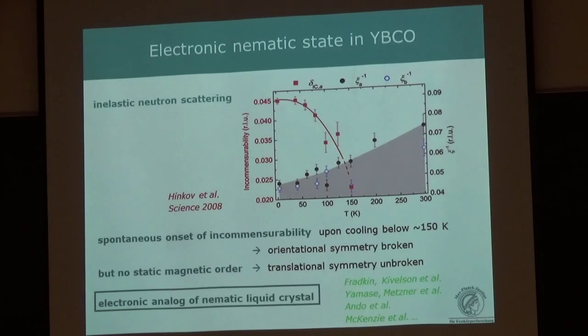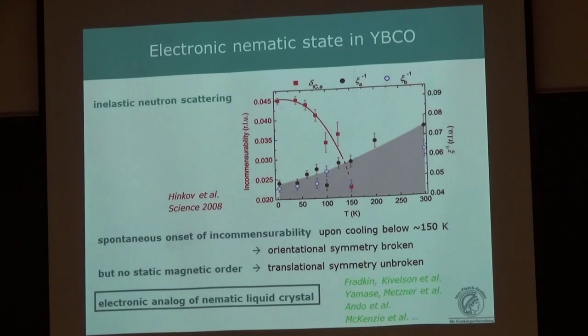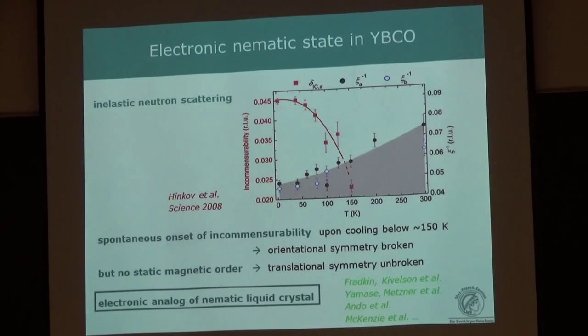Rather, this orthorhombic crystal distortion acts as an additional field—just like a field applied to a ferromagnet broadens the phase transition, but you can still call it a ferromagnet even though symmetry is already broken above the Curie temperature. This incommensurability was extracted from low-energy spin fluctuations; it's the same incommensurability that eventually characterizes the quasi-elastic peak at low temperatures. This incommensurability survives even in the absence of any kind of static or quasi-static magnetic order.